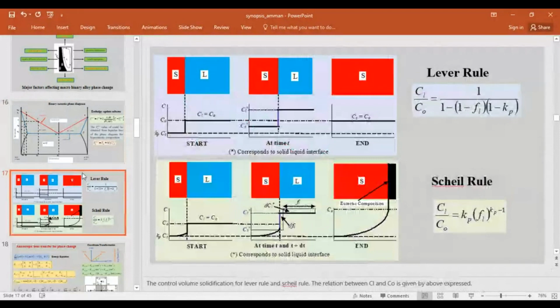So then coming to the lever rule. So if we talk the case of lever rule, here what you can see is this is the small cell we have taken. So in this small cell we have a solid phase and the liquid phase, right? So here there is a partition, okay, that is denoted by Kp, partition coefficient. So it is Cs by Cl.